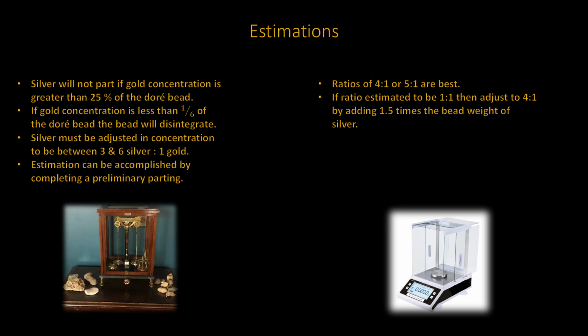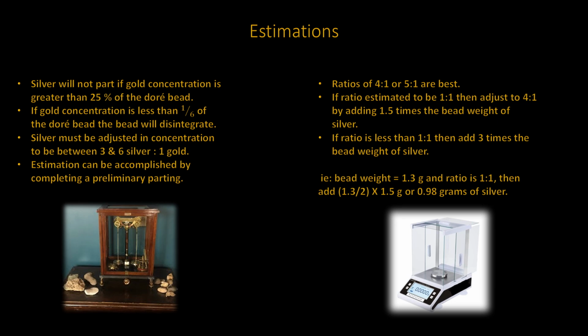If the preliminary parting suggests that the silver to gold ratio is 1 to 1, and you're looking for a 4 to 1 ratio, it can be achieved by adding 1.5 times the bead's silver weight in silver. If it is less than 1 to 1, then it is 3 times the bead's silver weight in silver. As shown in the example, if the bead weight was 1.3 grams at the start and it was estimated to have a ratio of 1 to 1, we would add 0.98 grams of silver for the inquartation.